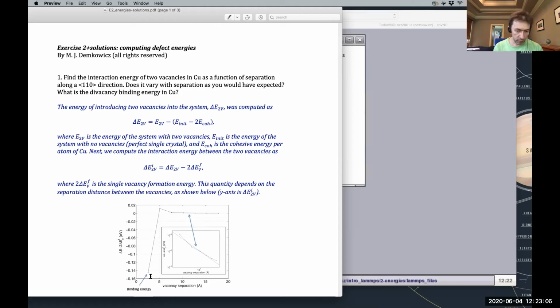Here I've plotted for you the binding energy as a function of distance between the vacancies. So you can see that when the distance between the vacancies gets large, the binding energy goes to 0, meaning the vacancies aren't bound at all. They're behaving as if they were just isolated vacancies. But if they're close together, if they're at a nearest neighbor location, right next to each other, then they bind to each other with an energy of about 0.14 electron volts.